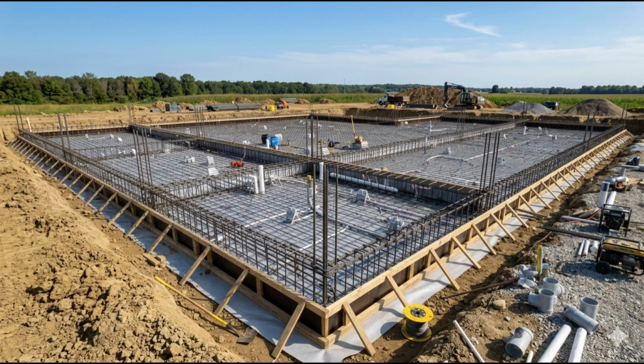The 28-day cubes were tested 4 weeks after the pour. The results from the 4 sets were as follows. Set 1, 42.3, 43.7, 41.9, 44.1 N/mm². Set 2, 43.2, 42.8, 44.0, 43.5 N/mm². Set 3, 41.7, 42.9, 43.1, 42.2 N/mm². Set 4, 44.6, 43.8, 42.7, 44.9 N/mm².